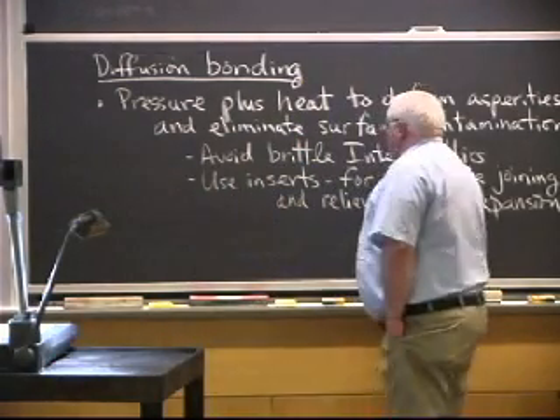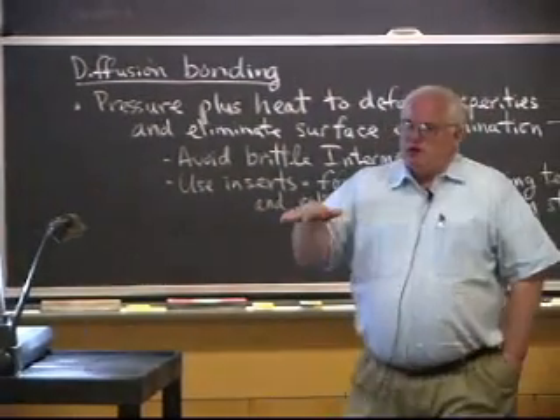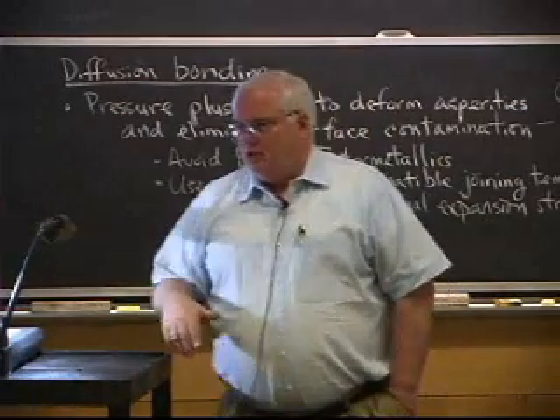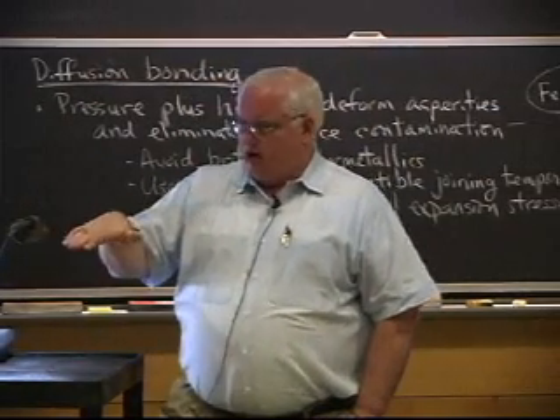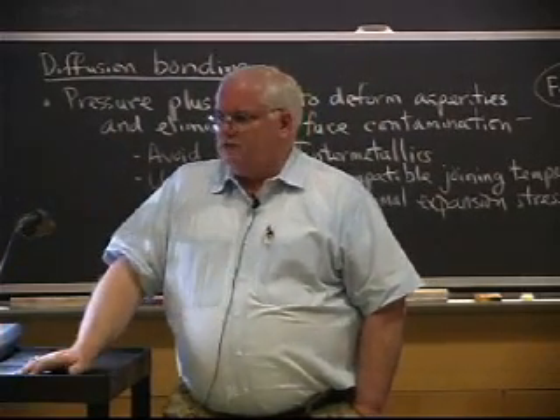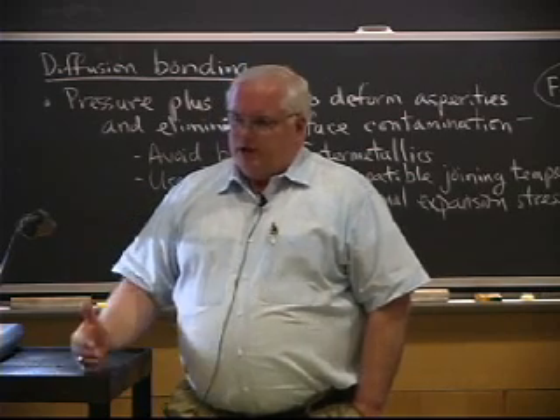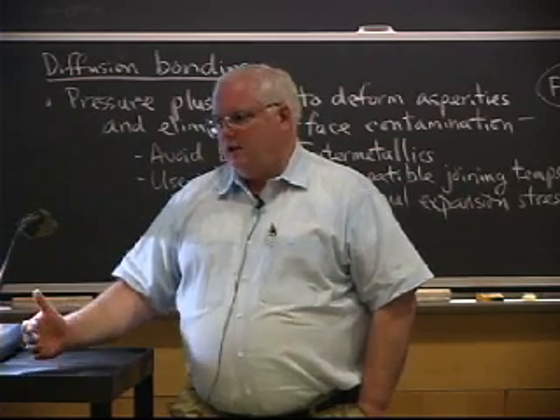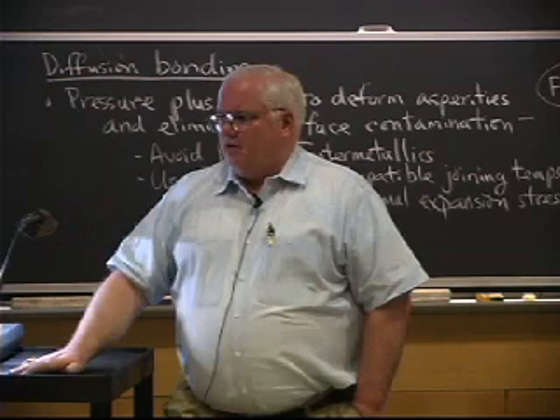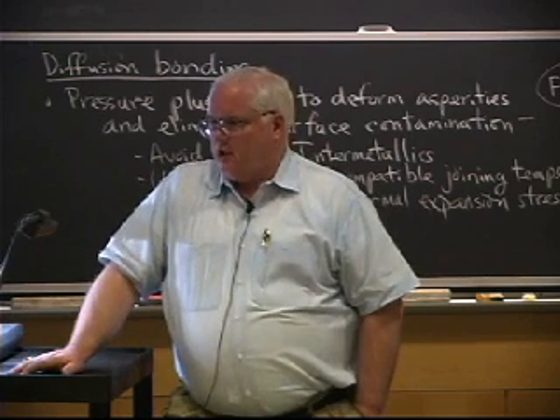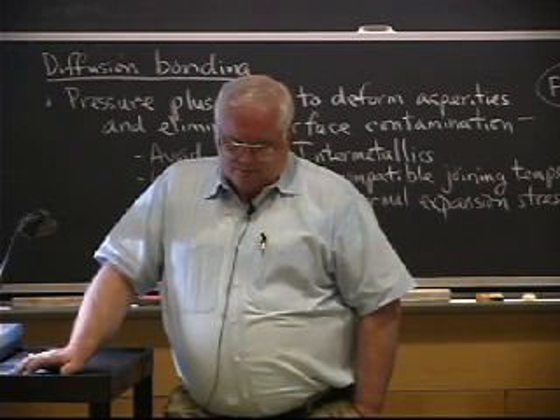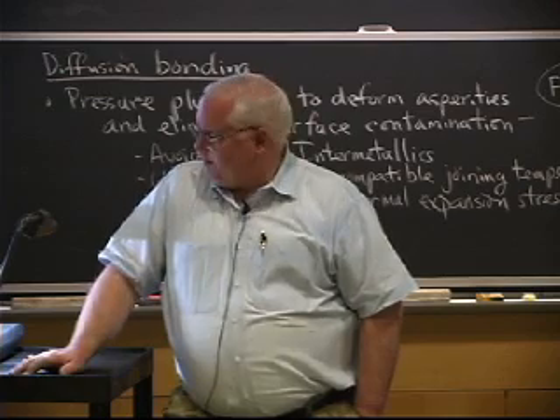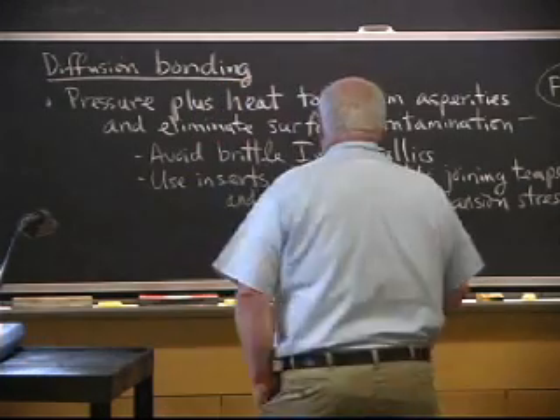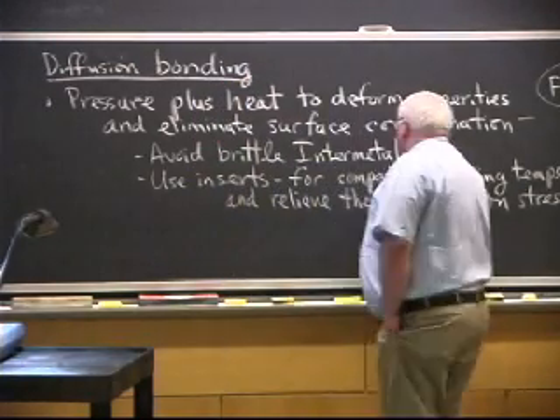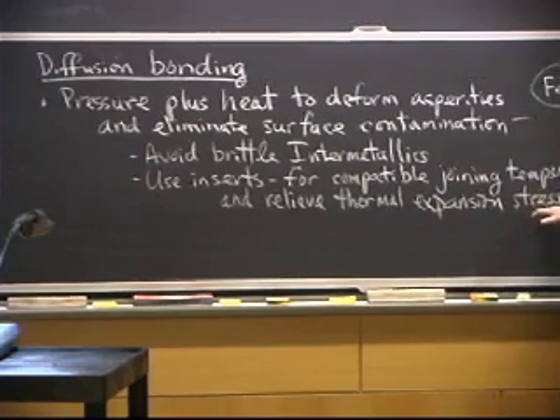They can be brittle. So if you put niobium, which is another refractory metal in the same part of the periodic table, in between, a sheet of niobium in between, it solves the problem because it doesn't form intermetallics with either tantalum or vanadium. And so basically you just got this layer. So it's a peanut butter sandwich with the niobium in the middle to avoid the brittle intermetallics. Also sometimes you use these inserts to relieve thermal expansion stresses.